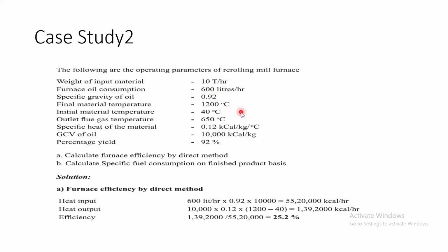Okay, then final material temperature 1200, initial temperature 40 degree, flue gas temperature 650 degree centigrade. If you remember in the boiler topic, I always kept on telling that the flue gas temperature should be as close as possible to 100 degree, or should be around 110 degree and all that. But here I am straightaway saying that the outlet flue gas temperature is 650 degree centigrade. It is really a waste. So ultimately, air preheaters or recuperators are a must in furnaces so as to recover this heat to the maximum possible extent. And that is the energy efficiency and the energy conservation we are going to study in this entire exam.